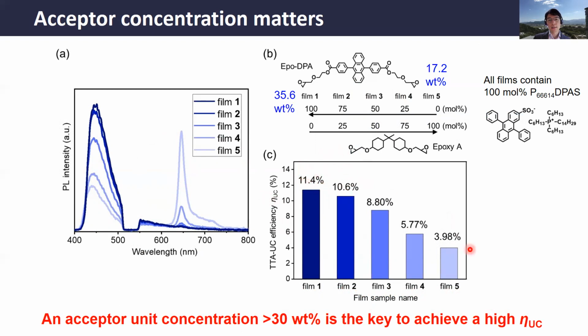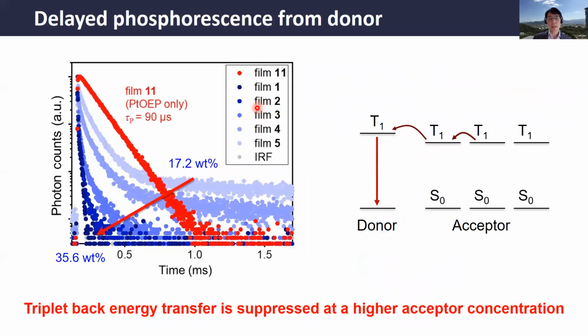So to understand this difference, we measured the phosphorescence decay, that is the donor phosphorescence. This red curve shows only PTOEP in the epoxy resin. And when we add the acceptor and increase the concentration, we observe these different decay curves. At 17 weight% of acceptor, we observed a decrease of the donor phosphorescence. This is because of the partial quenching of the donor phosphorescence by the acceptor.